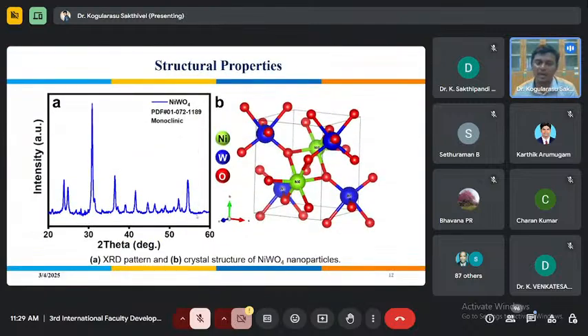So of course, when we prepare any material, checking the property is the first thing. So we went for the structural properties. So when we checked, it is as we expected. We got the monoclinic structure of nickel tungstate, and it is proven by the X-ray diffraction patterns. And this is how the crystal structure looks. And the morphological properties, we have examined it through TEM, transmission electron microscope, and the lattice fringes all came as expected, like a nanomaterial with the D-spacing.